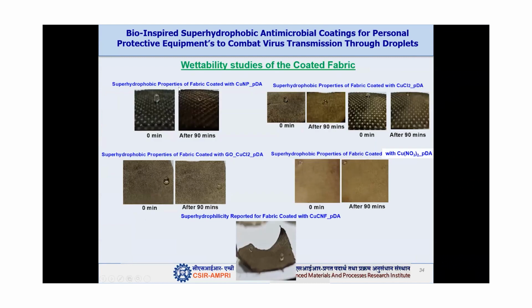We got the coating, and then we tested its wettability also. What we found is that these coatings are super hydrophobic in nature. This is at 0 minutes, when we put a drop on the fabric, and even after 90 minutes the drop is intact here. Here also you can see after 90 minutes the drop is still there. We related this to our present COVID situation: if somebody is sneezing, there is droplet transmission of the virus. Since this droplet even after 90 minutes is still on the fabric and not absorbing, due to the lotus effect it will actually drain out. So there are very few chances that this drop will absorb into the fabric and reach your mouth or nose area.